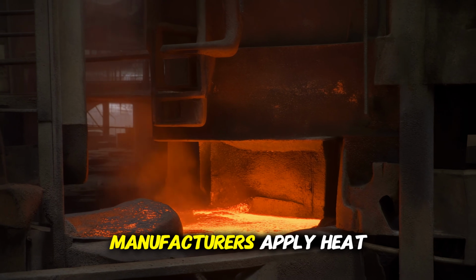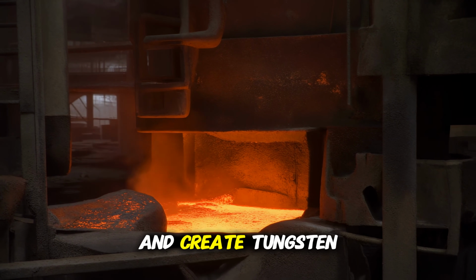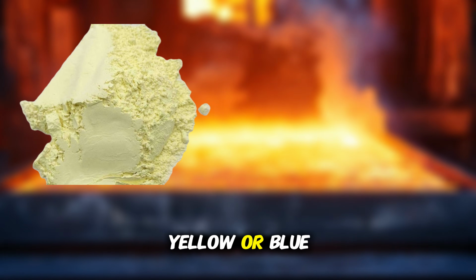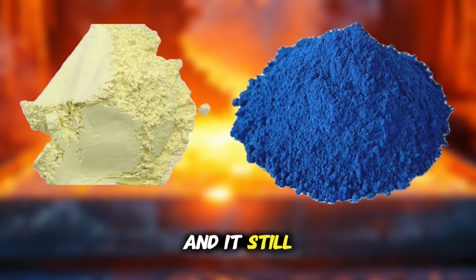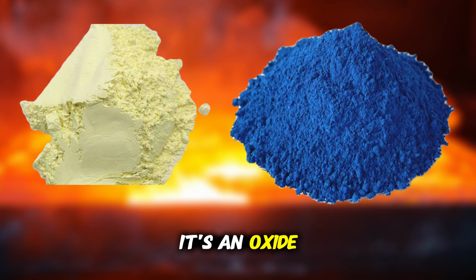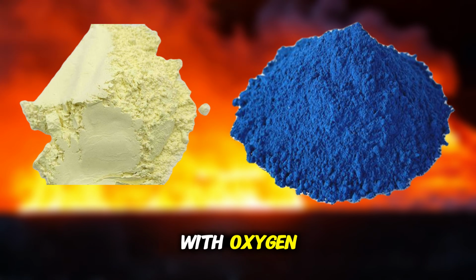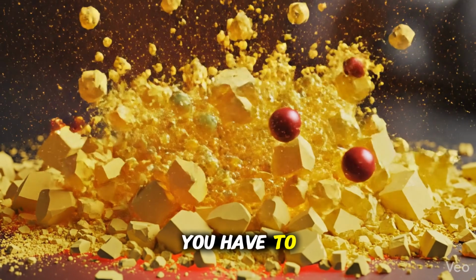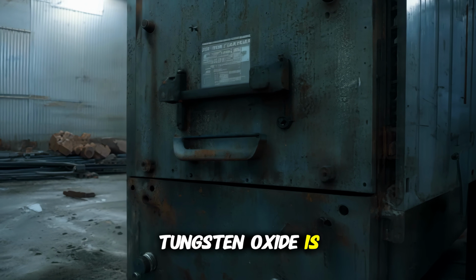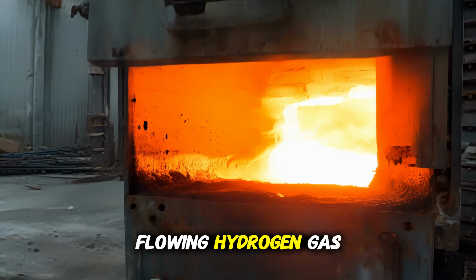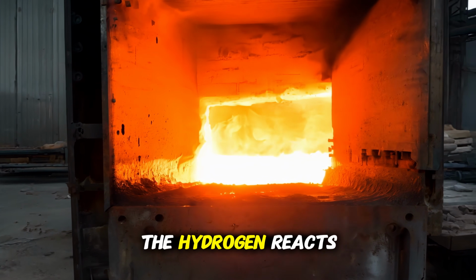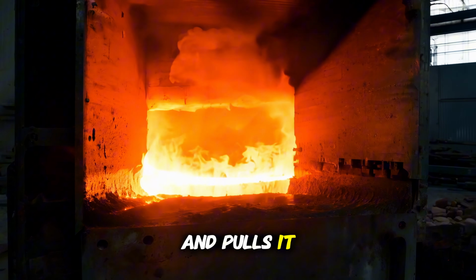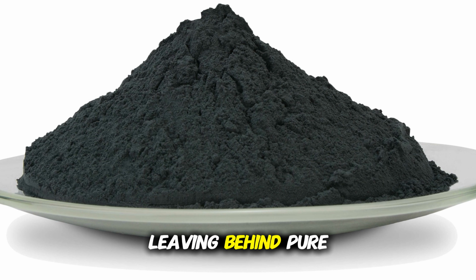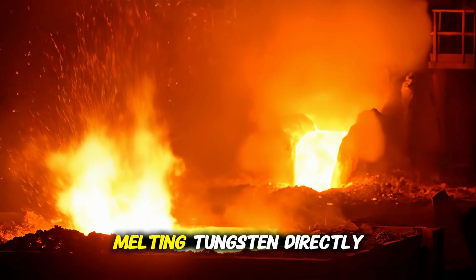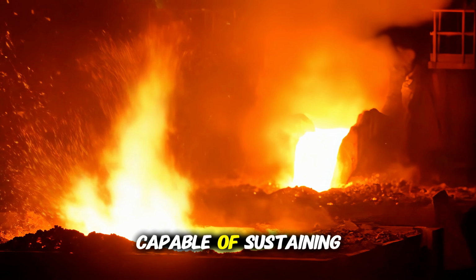From APT, manufacturers apply heat to drive off the ammonium and create tungsten oxide. It's a pale yellow or blue powder depending on the process, and it still isn't the metal itself. It's an oxide, meaning tungsten bonded with oxygen. To get to pure tungsten metal, you have to remove that oxygen. Tungsten oxide is placed inside a furnace and exposed to flowing hydrogen gas at high temperatures. The hydrogen reacts with the oxygen in the oxide and pulls it away, molecule by molecule, leaving behind pure tungsten in powder form.